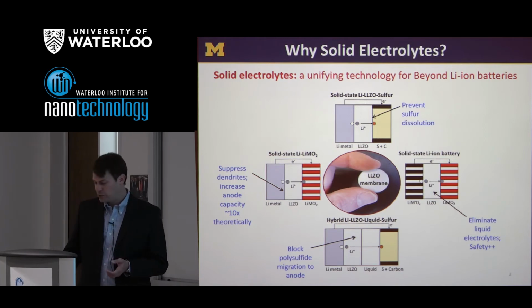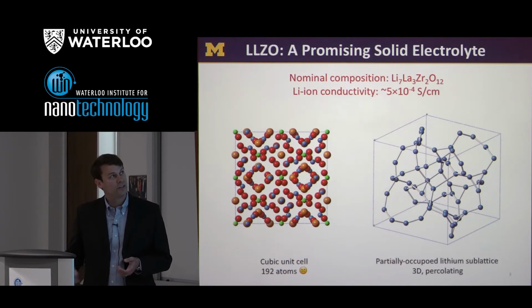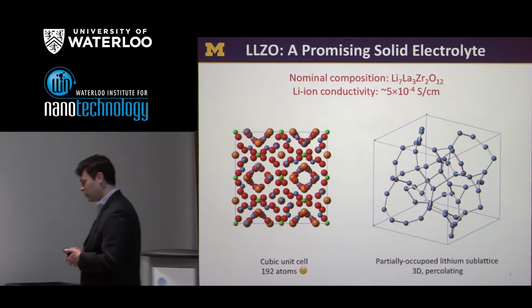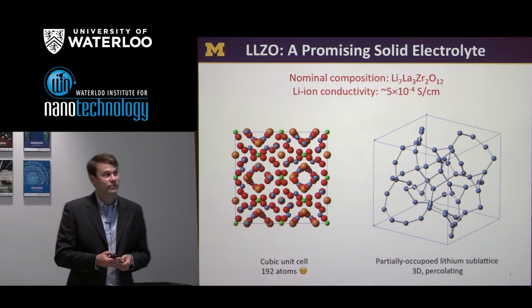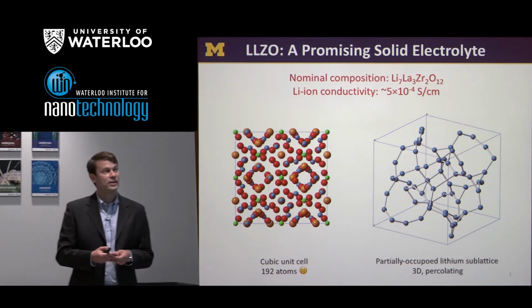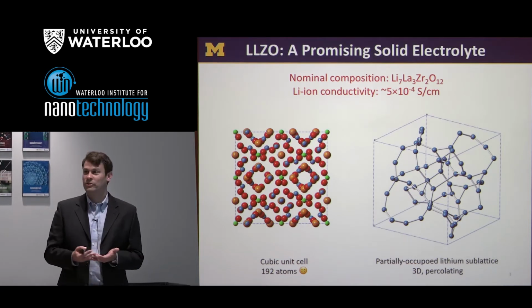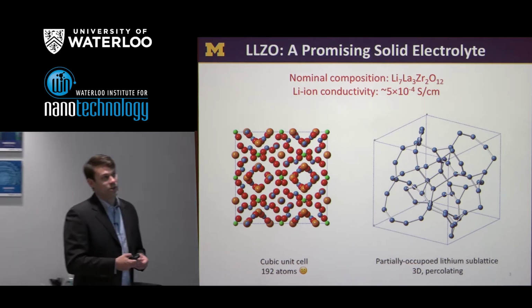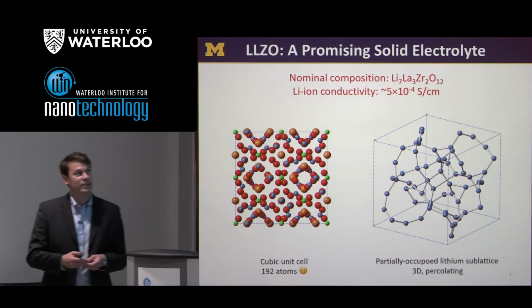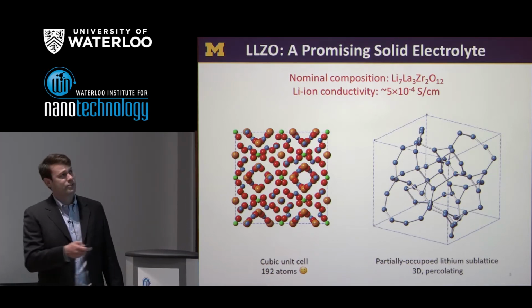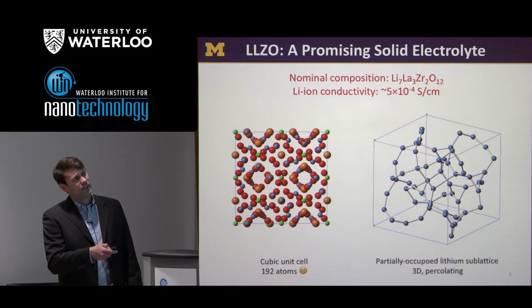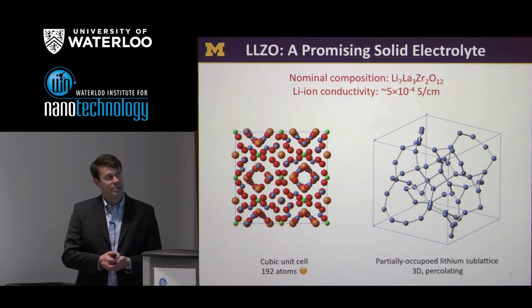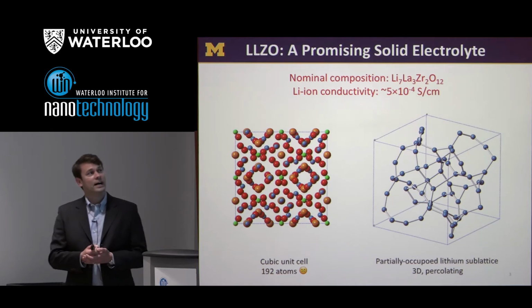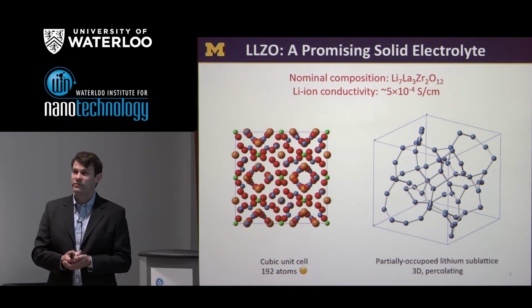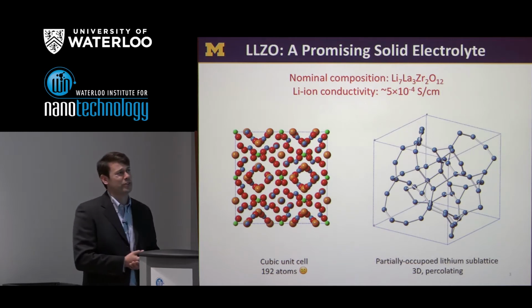So those are two really good reasons to focus on solid electrolytes. And like I mentioned earlier, we now have a handful of compounds that apparently have the requisite ionic conductivity to be a viable electrolyte. As I'll show you, there are some other challenges we need to address, and the vehicle I'll use for illustrating those challenges is this compound LLZO, which has the composition you see here. This guy has a conductivity of about half a millisiemens. This is approaching what we would have for a conventional liquid electrolyte, which would be about 1 millisiemens.